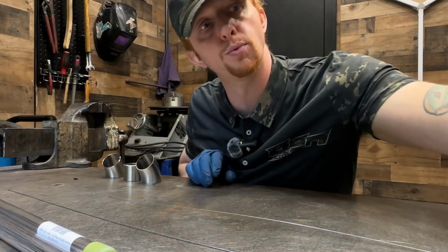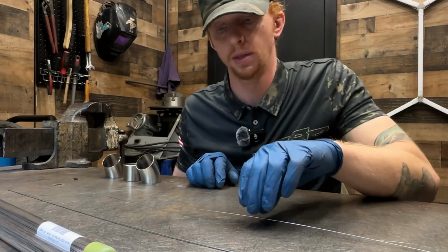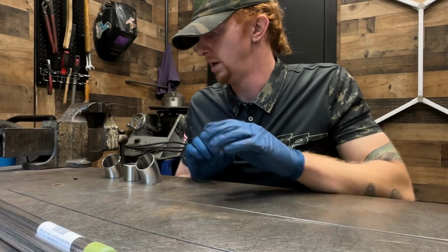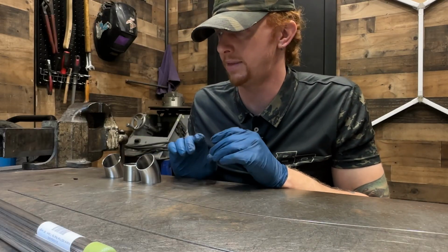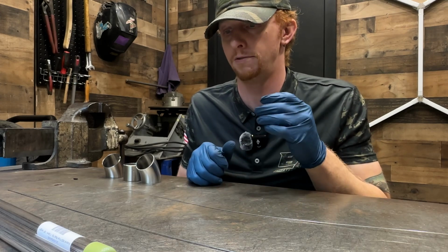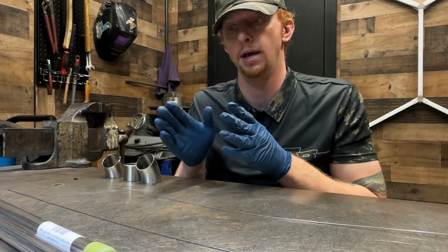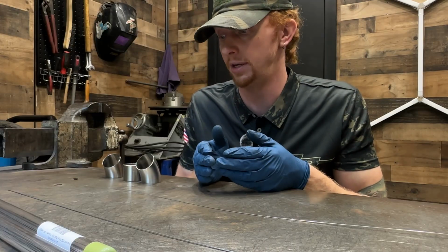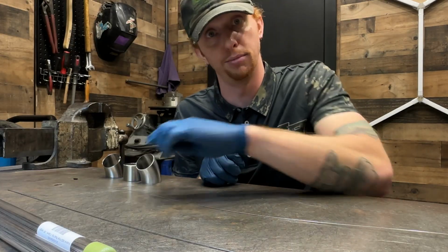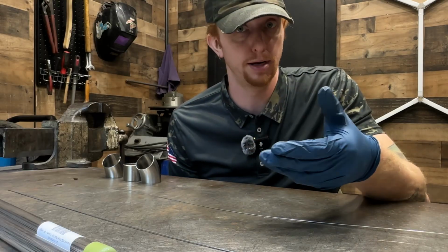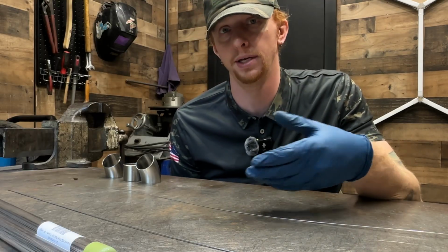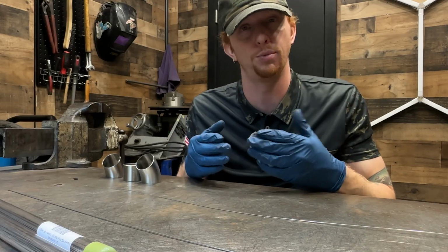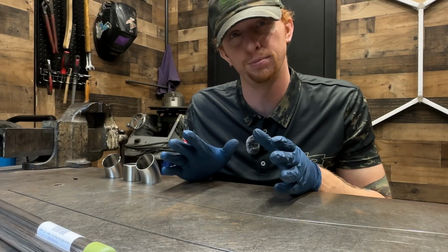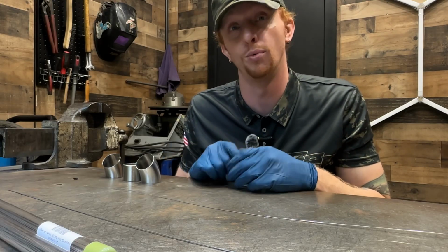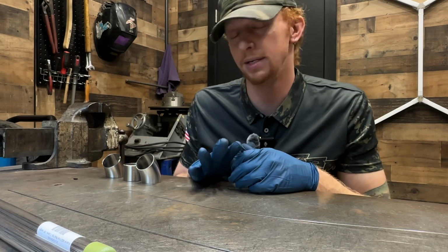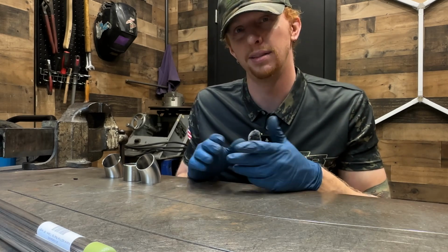For this weld, since we're going to be beginning with butt joints, I'm going to use the smaller diameter filler rod. Being that this material is so thin, with a thicker filler rod you can run into issues with the filler rod quenching or cooling the puddle off, and therefore causing it to be erratic and to move around in unpredictable and undesirable manners. I found that with thinner materials, thinner tubing, thinner filler rod generally works better to have a nice predictable weld, at least the way that I weld. So your mileage may vary on that. That's how I prefer to do it, and that's how we're going to do this right now. So with that being said, let's go ahead and gear up and run a couple of welds.